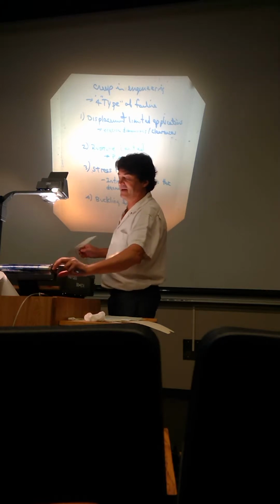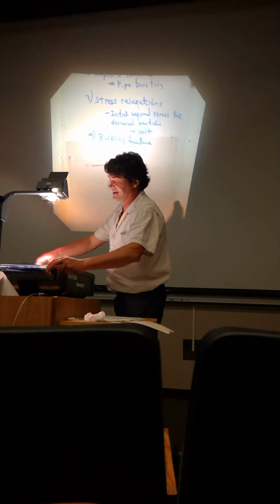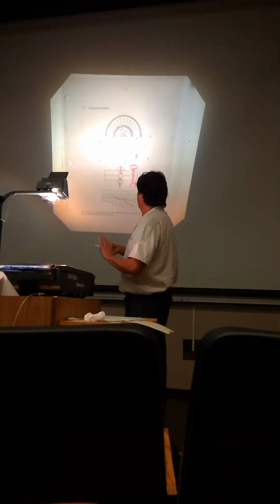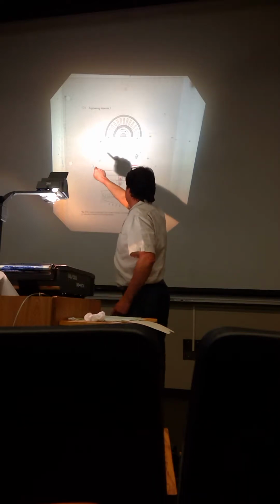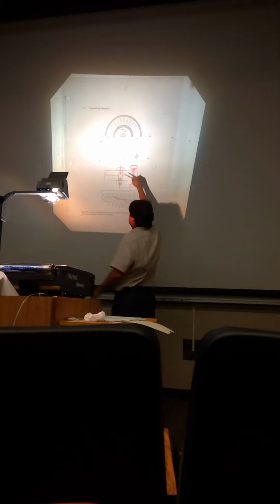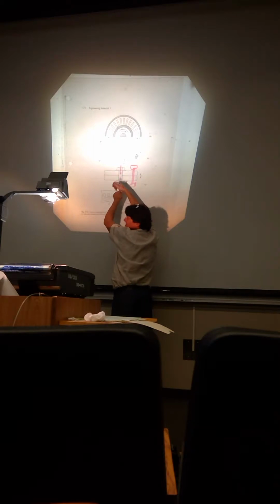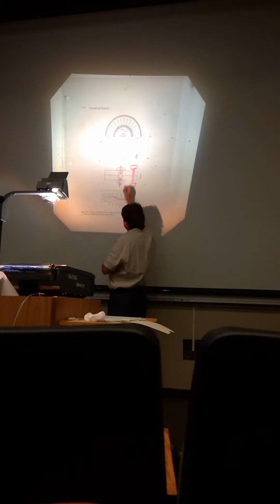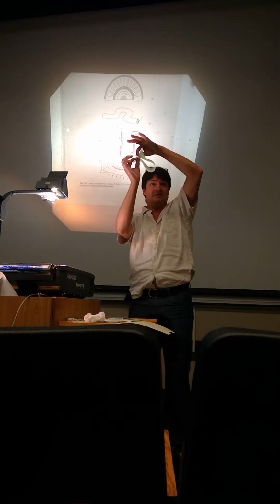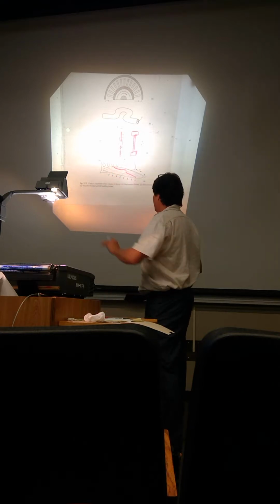And in Ashby, he's got nice pictures of these. I went through them here so you can actually see them. So here's an example of type 1. Your turbine blades, if those blades get too long and they hit the outer shell there, they'll fracture. This is more of a rupture limited. So here's a pipe with a pressure and you blow out your pipe. A bolt holding two pieces together has to have a certain pressure there to keep those from sliding. If that bolt loosens because it's stretched over time, you lose your clamping force. Example of an airplane wing, that if it starts deforming here, and again, buckling, remember what buckling is? It can do that, so it starts to deform and then all of a sudden it'll go very fast because the stress is out of plane, so you get buckling limited creep. So those are sort of 4 examples of how creep failures can occur.